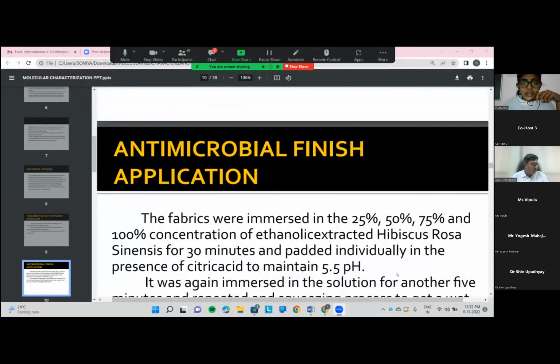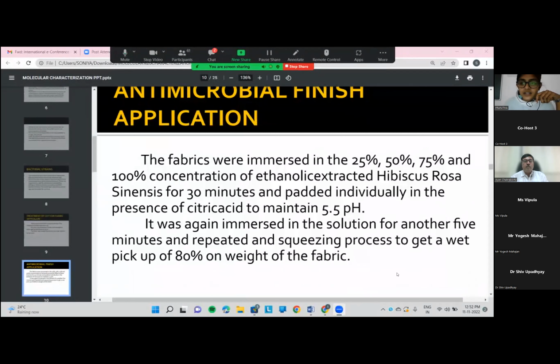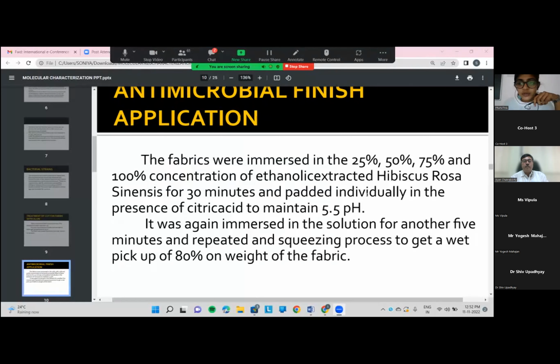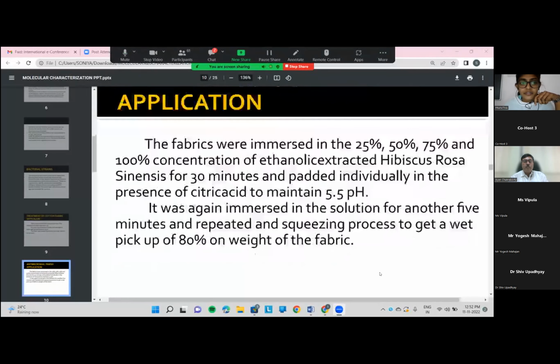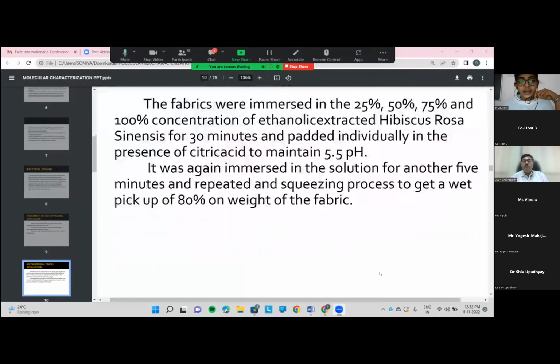The fabrics were immersed in the 25%, 50%, 75%, and 100% concentrations of ethanol-extracted Hibiscus rosa-sinensis for 30 minutes and padded individually in the presence of citric acid to maintain pH 5.5. They were again immersed in the solution for another 5 minutes, and the squeezing process was repeated to get a wet pickup of 80% on weight of the fabric.